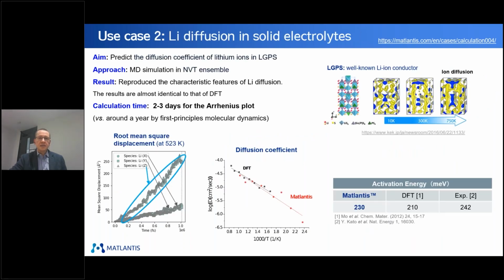The second use case is a different one, but it is related to lithium-ion diffusion in solid electrolytes, the LGPS to be more precise. Here, what we have done is run molecular dynamics simulations. The goal was to reproduce the characteristic features of lithium diffusion. And we have done that in 2 to 3 days in order to plot the Arrhenius plot that you have on the screen here at the bottom left.